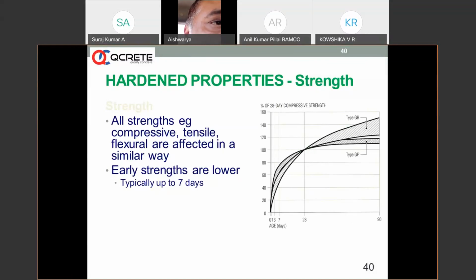Hardened properties: the most important and beneficial hardened property is the alarming increase that you can encounter when you are using blended mixes. GB stands for blended mixes against GP, that is the OPC mix actually, where the OPC curve after 28 days becomes horizontal, or the strength becomes stagnated, and you can see a very significant improvement after 28 days, between 28 days and 90 days.